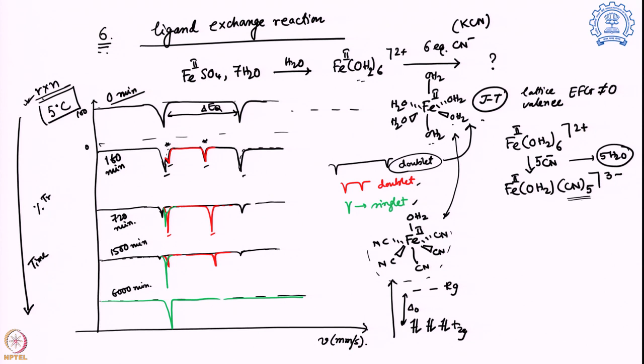That is a huge change when it is exchanging water versus cyanide. Water is a sigma donor, pi donor. It prefers high spin. Cyanide is a sigma donor, pi acceptor. It prefers a low spin system. And in this case of low spin, you have an iron 2 d6 system like this, all paired up, so there will be no valence contribution to the EFG.